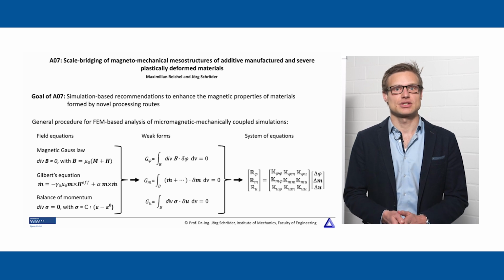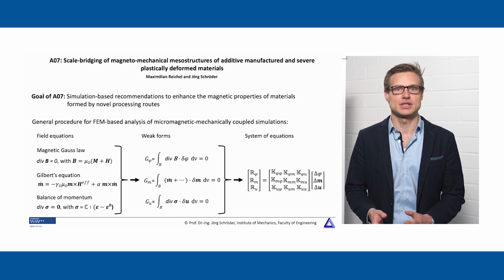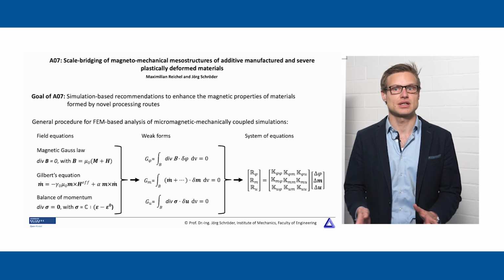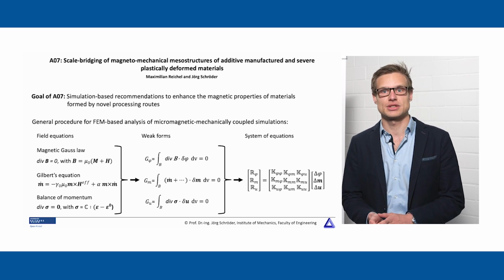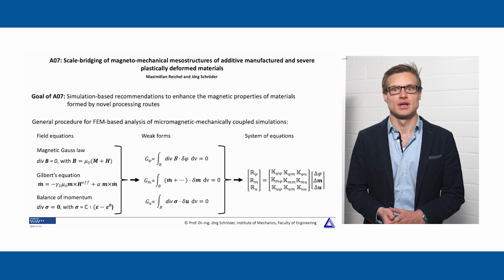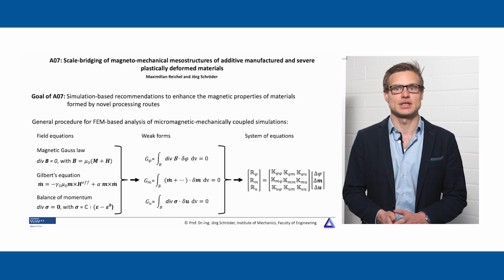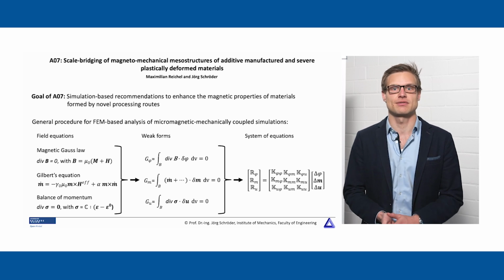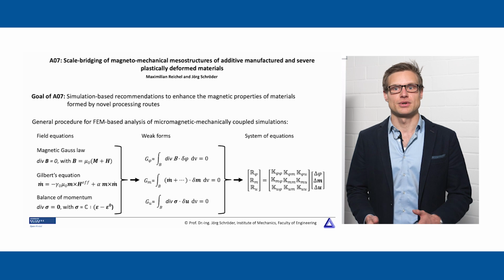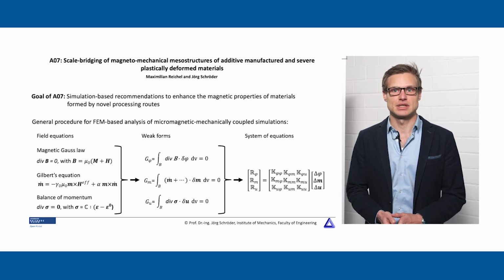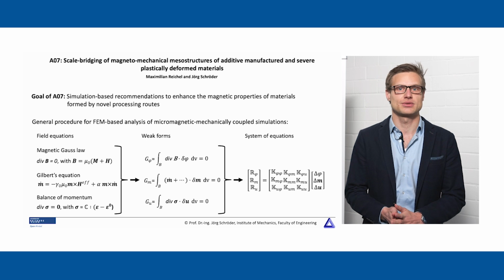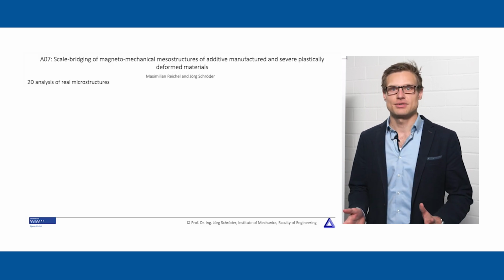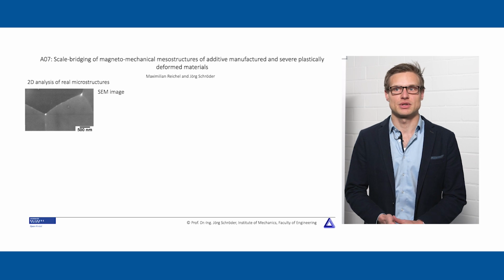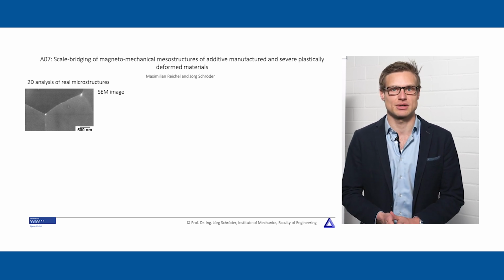The implementation of such an FE framework follows a fixed procedure, starting with the field equations that are the magnetic Gauss law, the Gilbert equation, and the balance of momentum. Those three equations are transferred into their corresponding weak forms using a variational approach. These weak forms can now be utilized to derive a system of equations that is solved using an iterative Newton-like method. The definition of a boundary value problem in the simulation framework starts with the geometry, like the SEM image of a given neodymium iron boron microstructure.